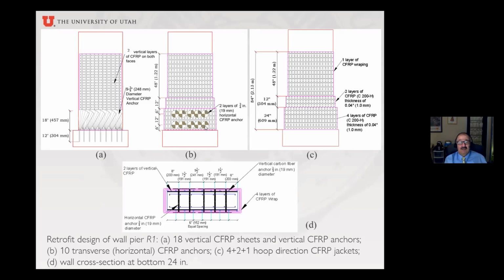You can see it here. 2 layers. Each layer, that we call these transverse anchors. Each layer has 5 anchors. These anchors are 3/4 inch diameter again, and they are splayed, as you see, 360 degrees. Below the anchors and above the anchors, there is also carbon fiber sheets in the hoop direction, meaning going all the way around the wall. So there are quite a few layers of those.